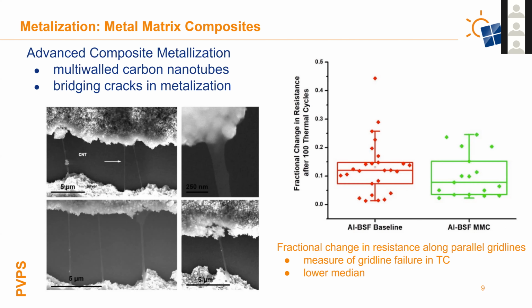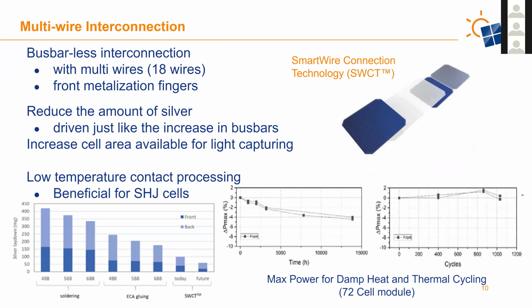Another thing to think about is multi-wire interconnection. These are bus-barless interconnections with multi-wires—about 18 wires—and they still have front metallization fingers. One driving force behind this, as Gerno had said, is wanting to reduce the amount of silver used, since silver is expensive. Just like increasing the number of bus bars, we can decrease the amount of silver used. It also increases the cell area, so we get better light capturing.